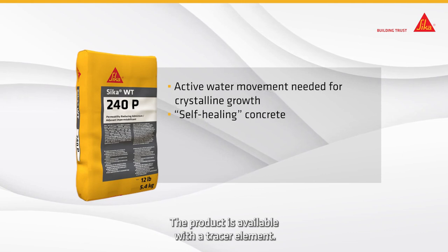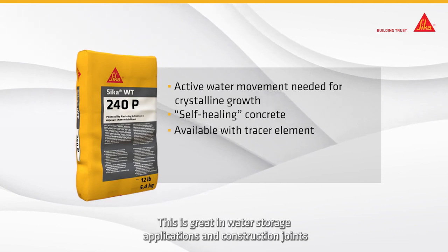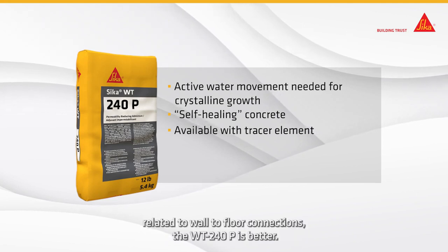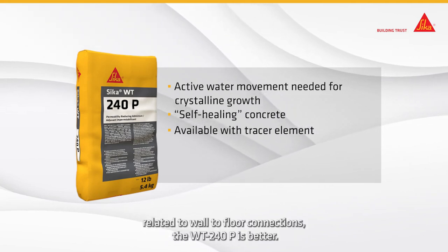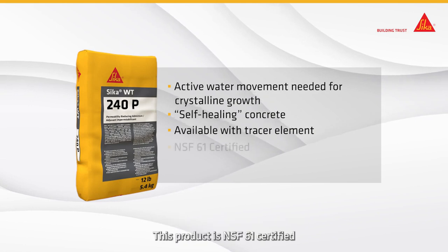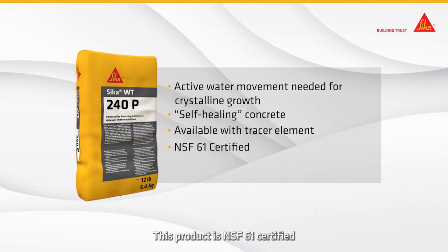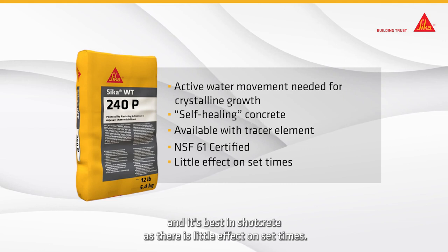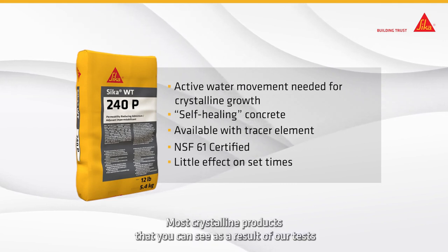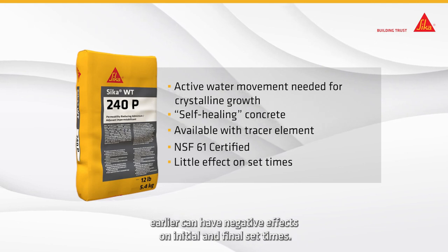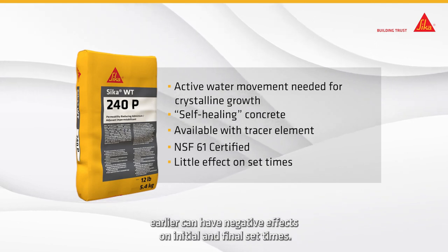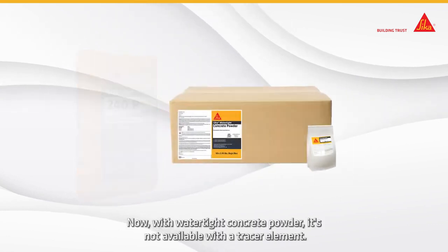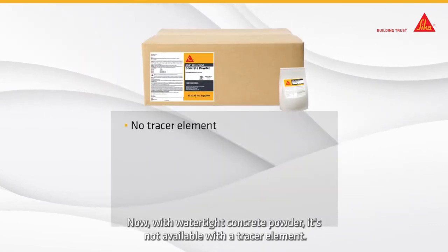The product is available with the tracer element. This is great in water storage applications and construction joints. Related to wall-to-floor connections, the WT240P is better. This product is NSF 61 certified, and it's best in shotcrete as there is little effect on set times. Most crystalline products that you can see as a result of our test earlier can have negative effects on initial and final set times. Now, with watertight concrete powder, it's not available with a tracer element.